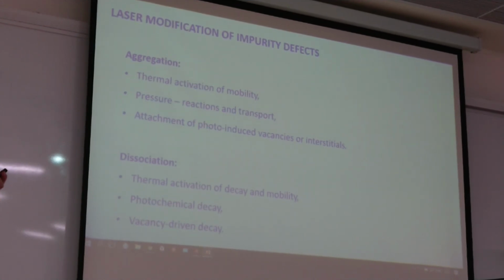And finally, if we produce vacancies and interstitials by photolysis, these species can attach to impurity defects, like in the case of nitrogen above. On the opposite, laser can induce dissociation through activation of decay of centers and their mobility. Also, dissociation can occur through photochemical decay and vacancy-driven decay.